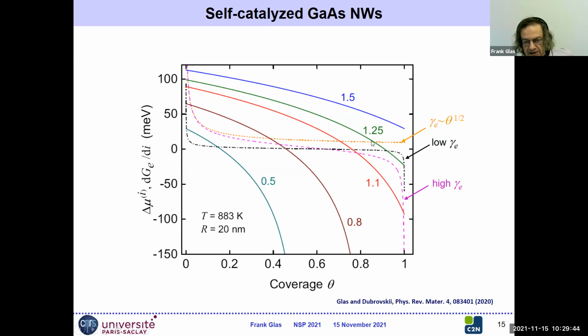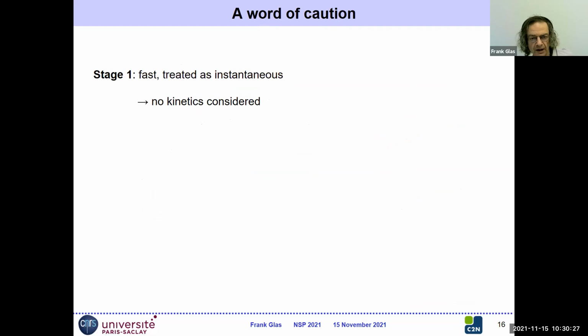But we can have cases, this 1.5 here, where if we take the standard bulk energy of the monolayer, we have an intersection. But if we have a large non-monotonous step energy, the violet curve here, we don't have any intersection anymore. So in this case, we could say that the stopping effect that we would have expected with the increasing step energy is suppressed in the case of the non-monotonous step energy. But you see that maybe it's not such an important fact, because it only occurs, at least in the self-catalyzed gallium arsenide nanowires for the size that I've chosen, in a narrow window of the initial concentration of arsenic in the liquid. So it's possible, but maybe not that important. So a word of caution.